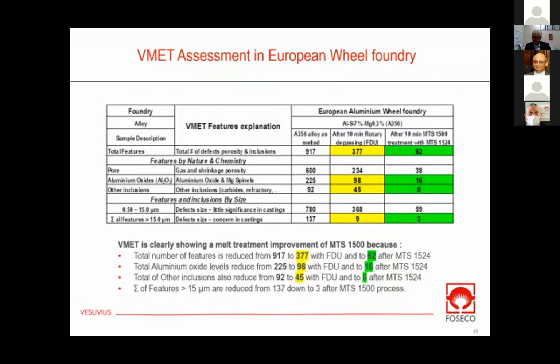About 10 years ago, we went to a very famous European wheel foundry using low pressure A356 alloy. We took a VMET sample of the melt, the column A356, the white one. And you can see we have found, and that's normal in a melter, when you melt ingots or chips or scrap, you create a lot of oxide. So this is expected, okay.